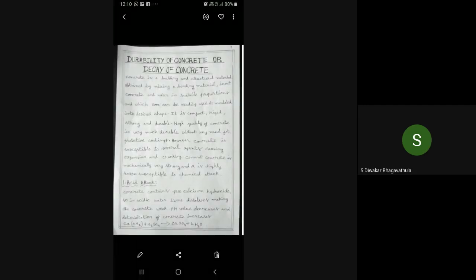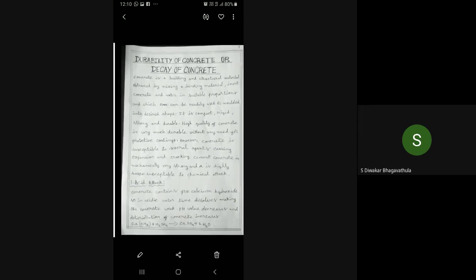The second type of attack is sulfate attack. Sulfates are present in soil, groundwaters, and marine water environments. Sulfates react with tricalcium aluminate to give bulky products, causing cracks due to expansion. This is avoided by using sulfate-resistant cements, which contain less tricalcium aluminate. Such danger is avoided by eliminating tricalcium aluminate from the cement composition and replacing it with tetracalcium aluminoferrite.